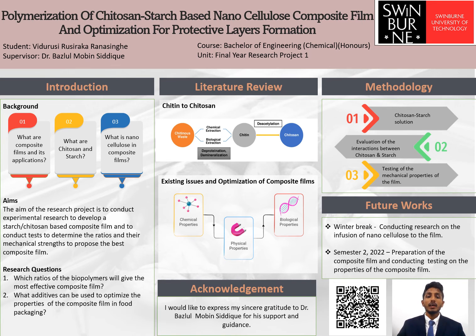The mixture will be cast onto a Teflon coated glass plate. After drying the films at room temperature for at least 72 hours, they can be peeled from the plates. Then they should be conditioned at 50% relative humidity at room temperature for 48 hours prior to testing.